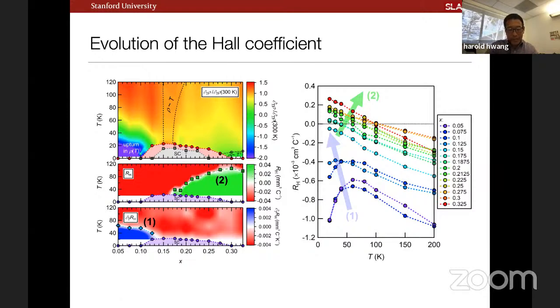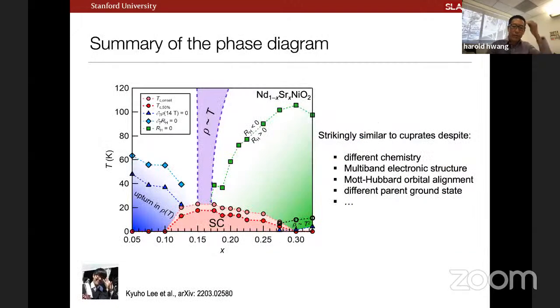So, this is very suggestive. We don't actually know at this point whether or not this is a coincidence of this multi-band structure, but certainly there's a lot of action around the superconducting dome, and we can summarize all of these transport features in this phase diagram. To say again, we see an upturn in resistivity that we think might be related to this stripe instability. And I should mention that this is qualitatively somewhat similar and reminiscent of the log T-like upturn seen in 214 cuprates.